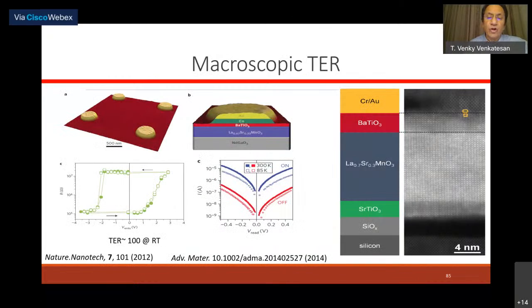Okay, so this is basically what you will see if you build essentially a tunnel electroresistance device. The barium titanate is the ferroelectric. You have a bottom metal, barium titanate, and a top metal. Such a vertical structure will give you resistance versus voltage characteristics that show very beautiful hysteresis. This field got kind of crazy, like GMR, and people started putting many, many layers in between. And every time you introduce a layer, the on-off ratio would skyrocket. So now people get on-off ratios of like 10 to the 5, 10 to the 6. So it's been somewhat crazy, and nobody understood what is really going on.